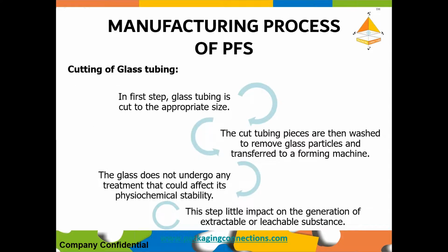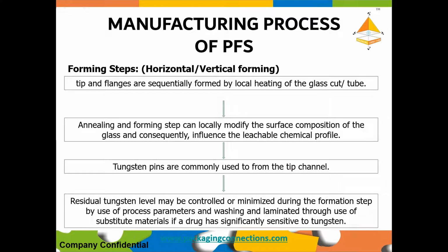So this is a slightly better explanation of forming. Forming steps explained better. Tip and flanges are sequentially formed by local heating of the glass cut tube. Then it moves to the annealing, because there is a lot of stress inside the glass when the forming is happening. It needs to be all evened out. And the right annealing is also important for a stable chemical profile. Otherwise, it could also lead to a lot of leachables.